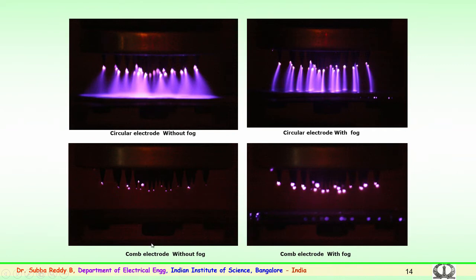So, this is again a similar pattern which is being taken for the comb type of electrode. Initially I was saying circular type of electrode for uniform discharge generation, then comb for non-uniform. You see the discharges, this is for without fog. In case of with fog, the intensity of the discharges increases, and this will affect the sample.